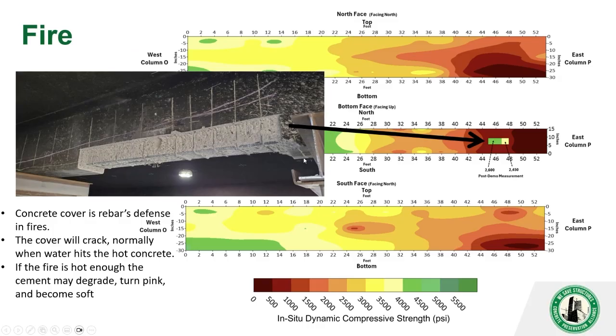It was terrible. We shored it up, and then we removed the concrete cover because your concrete cover is what makes concrete a fire resistant material, a non-combustible material. So it has to make its way through the cover. Because we had good cover, you can see right here, we had 2 inches of cover on all sides. The concrete cover was cracked, but once we got down inside the reinforcing gauge, the strength of the concrete came right up. So it was down in this region right here. So the strength comes up the further in you go.